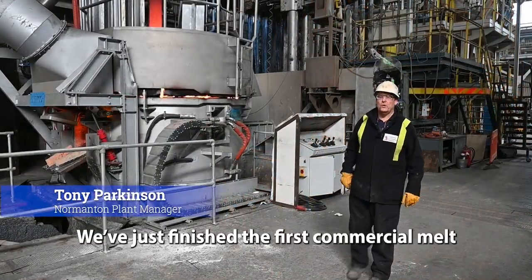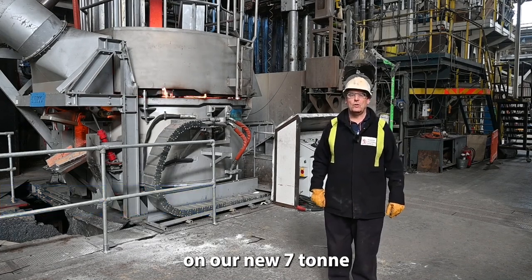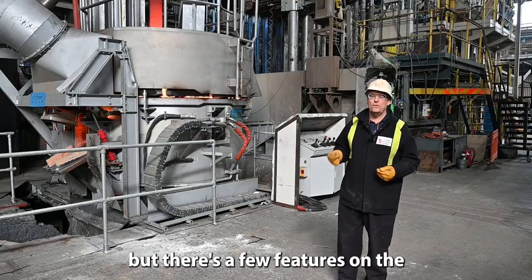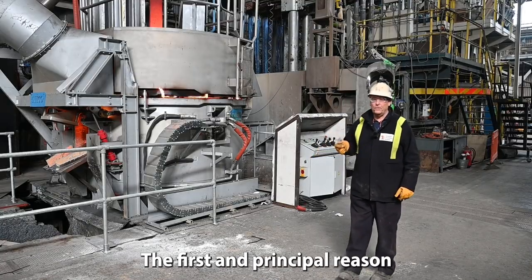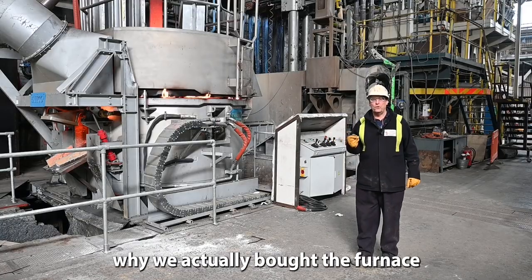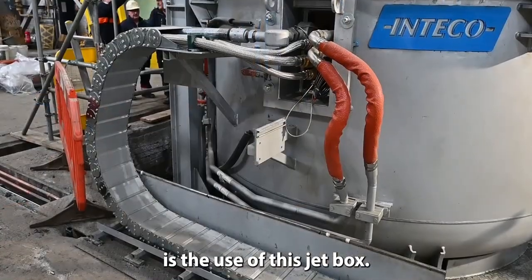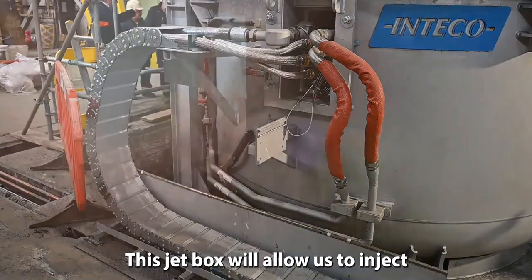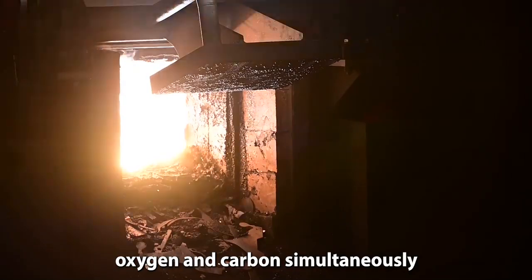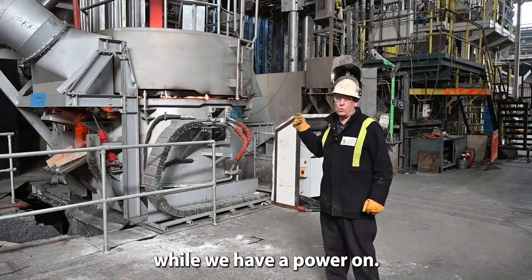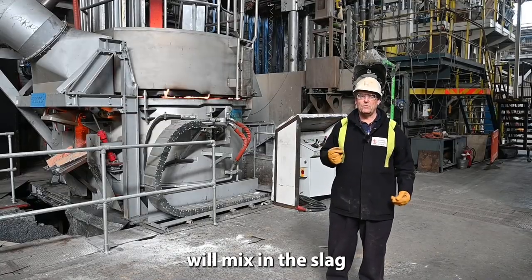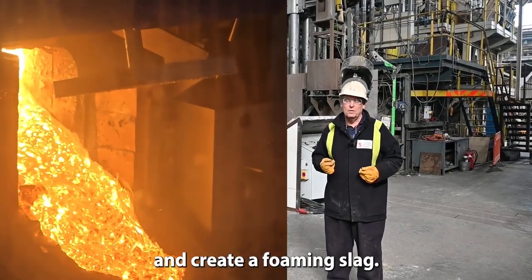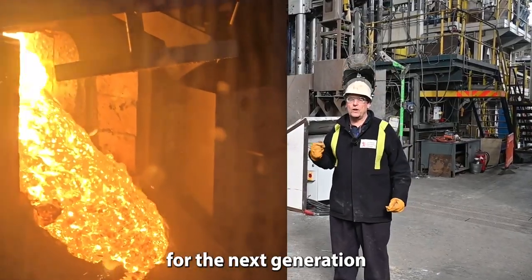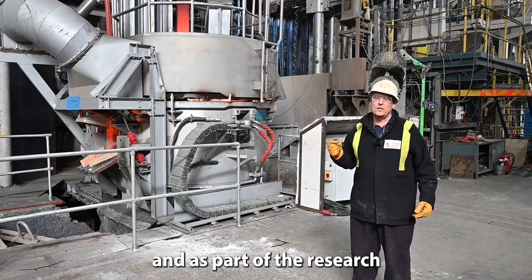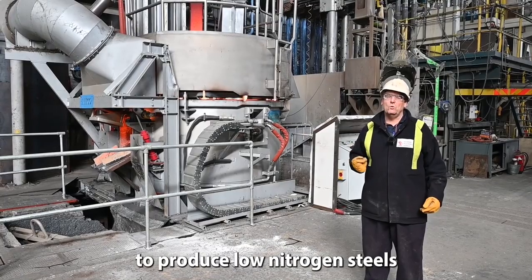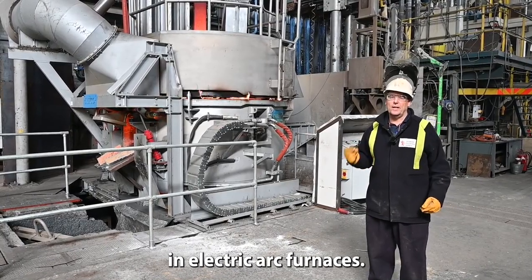We've just finished the first commercial melt on our 7-ton electric arc furnace. But there's a few features on the furnace I'd like to point out to you. The first and principal reason why we actually bought the furnace is the use of this jet box. This jet box will allow us to inject oxygen and carbon simultaneously while we have the power on. The carbon and oxygen will mix in the slag and create a foaming slag. This is really important for the next generation of steels and slags, and a part of the research which is required to produce low nitrogen steels in electric arc furnaces.